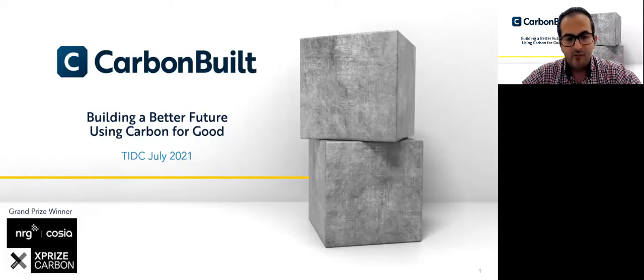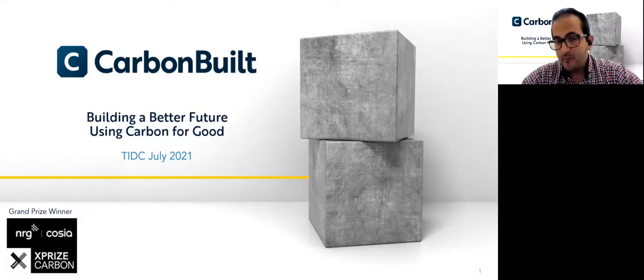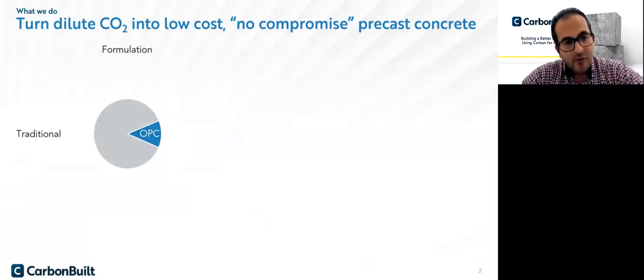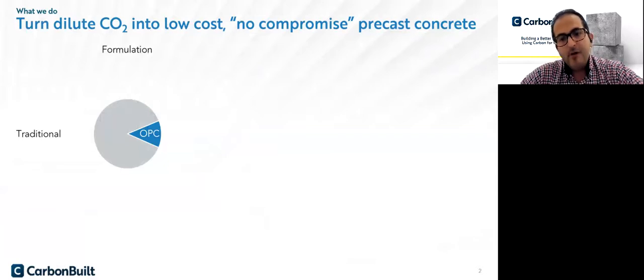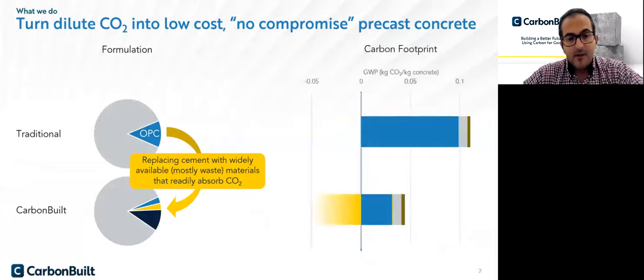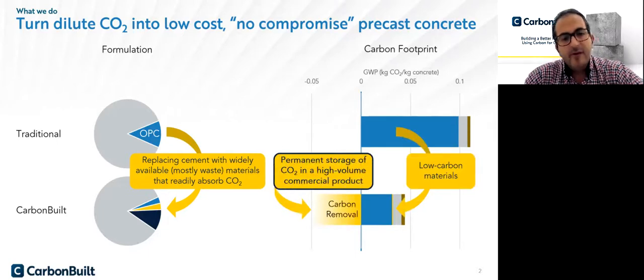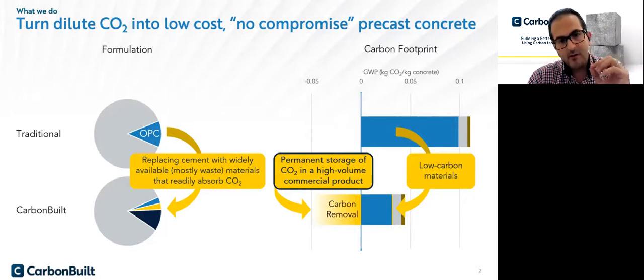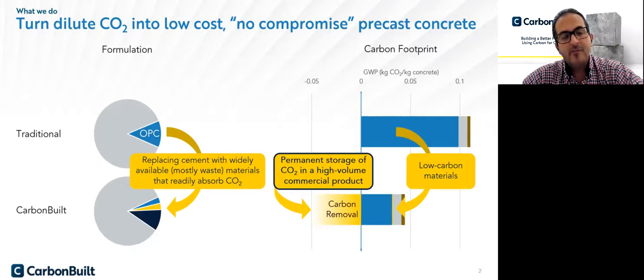There have been some attempts using similar technologies for carbon dioxide utilization in concrete, but they are mainly expensive and require high temperature or high pressure. The CarbonBuilt technology converts carbon dioxide into precast concrete components without compromising performance. The benefit is twofold: one is displacing cement with a substantial substitution using low cost, low carbon materials like fly ash and slag. The second benefit is the permanent storage of carbon dioxide during this process. The combination of CO2 avoidance and permanent carbon dioxide removal enables us to reduce the carbon intensity of concrete by up to 80%.